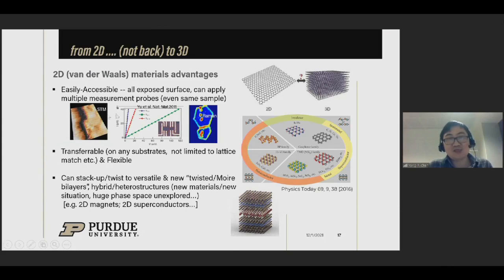So you can apply many different measurement techniques, scanning probe, optical, imaging, or transport, potentially even on the same device or same sample. They can be transferred on almost any substrate. So you are not limited to the traditional, for example, epitaxial lattice matched growth of these 2D systems, and they're very flexible. Perhaps most importantly, and a very good new situation that I highlighted in the beginning, important for new discoveries to be made, is that you can bring different layered 2D materials together to make totally new kinds of structures, not just these twisted bilayers, but also these stacked van der Waals heterostructures, potentially in some sense going back to 3D, but not to the old material where these 2D layers come from, but in new combinations, new situations.